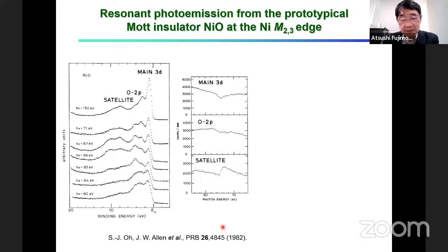So it's one of the very early works by the Stanford group for the prototypical Mott insulator nickel oxide at the nickel 3p to 3d core absorption region. This data shows that near the absorption region, the so-called satellite is enhanced, and the so-called main band does not enhance or is even suppressed. So the enhancement occurs in the satellite. This is an unexpected result because enhancement was supposed to occur in the d states, the main band, but actually the d state is not enhanced, but even suppressed.